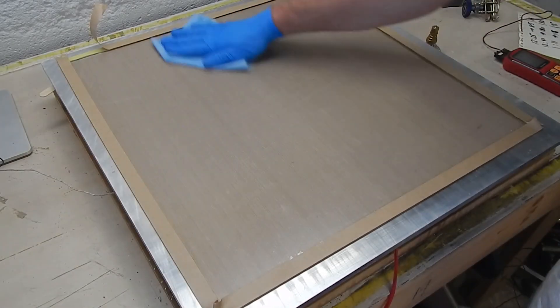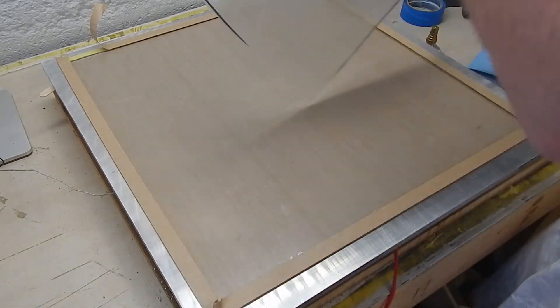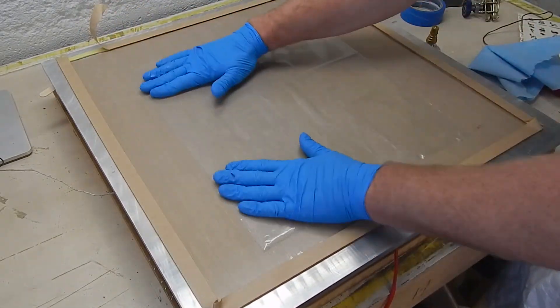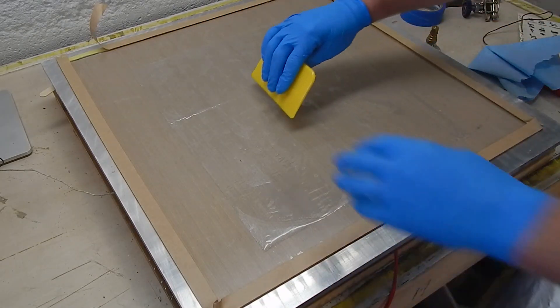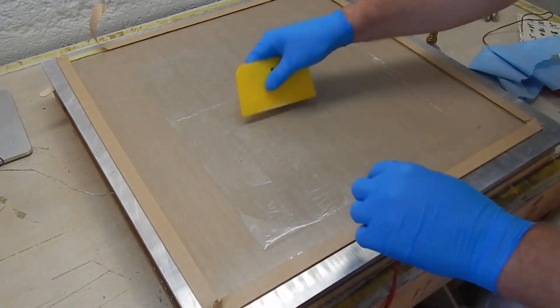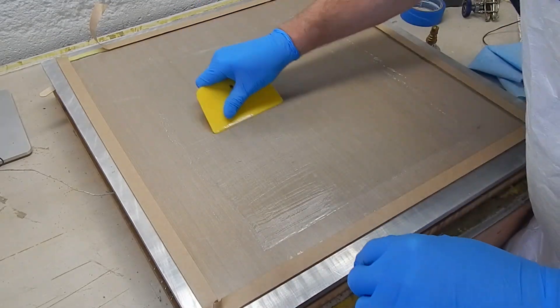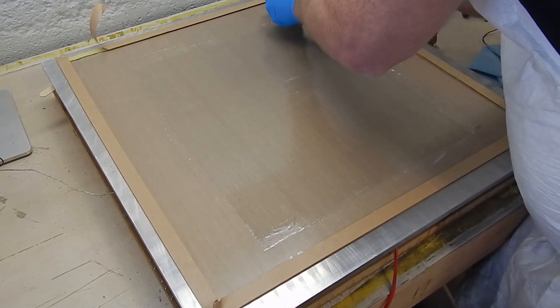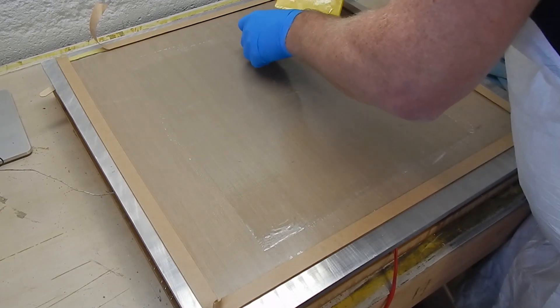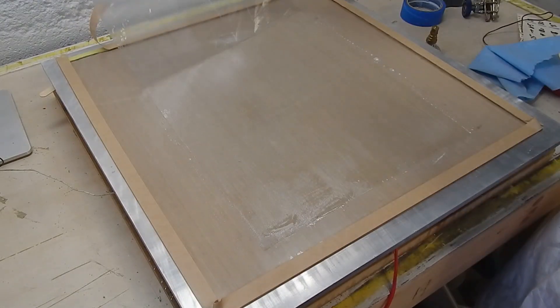So I'm going to lay this up on this table. It has some Teflon on it. Sometimes it's hard to pull the plastic off. But I got it off one side. Leave it on the other side. So I'm actually just touching plastic here, not the laminate. Especially with this really thin glass which you can mess up so easily. Then I grab the squeegee again and work out all the air with that plastic layer still on top. And this is a nice way to make sure that you have a good surface finish even when you don't have that much resin. Peeling the plastic off here it's kind of a hassle. It's easy to catch the edge if the glass isn't perfectly square. Sometimes one way works better than the other. And so there's the glass. I'm going to put the honeycomb right down on top.